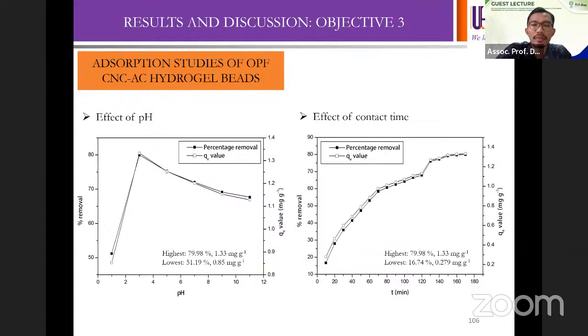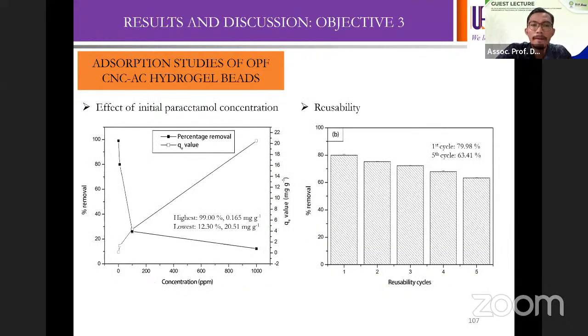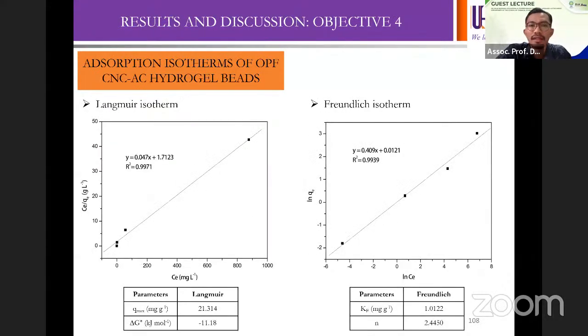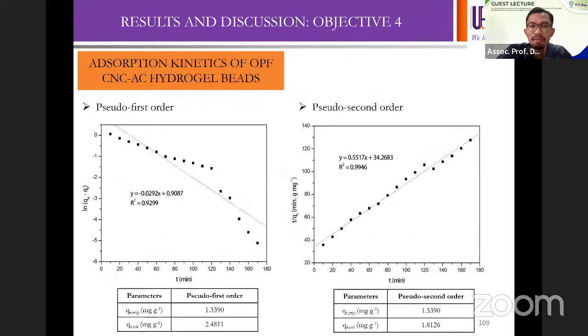So several optimization studies have been done. We did the contact time, pH, reusability as well. And we can see that the adsorbent can be reused as much as 5 times or 5 cycles. And for the adsorption isotherm studies, we found that it fitted best with Langmuir, with delta G values around -11. So mostly the interaction is physical adsorption. And it actually fitted best with pseudo second order for the kinetic studies.